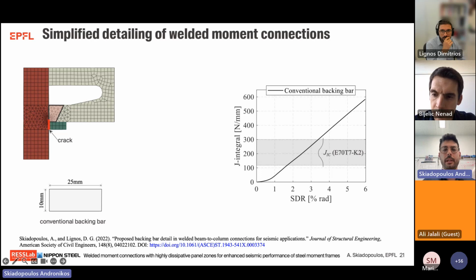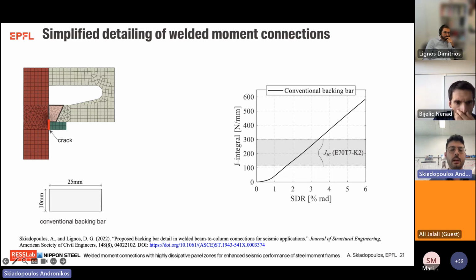By comparing the fracture potential with the typical fracture toughness of weld electrodes utilized currently in the seismic norms, we see that such a connection is not able to withstand lateral drift demands exceeding 2%, which, as I also said before, is characteristic of the design basis event, earthquake event, which is not an adequate performance to have. The primary reason for this is that once we have a backing bar in place, this may impose a crack that penetrates through the beam flange thickness, and therefore the beam loses the maximum moment capacity that it is able to sustain, since now less flange thickness is utilized in sustaining this moment.